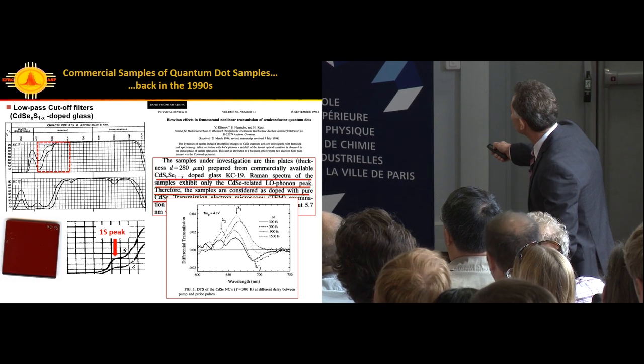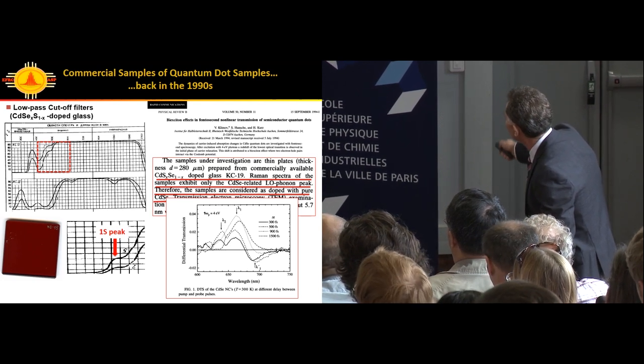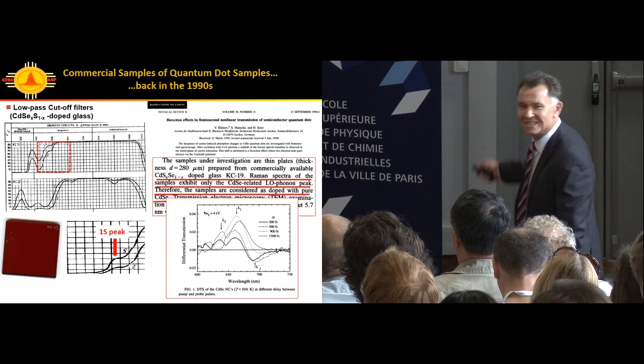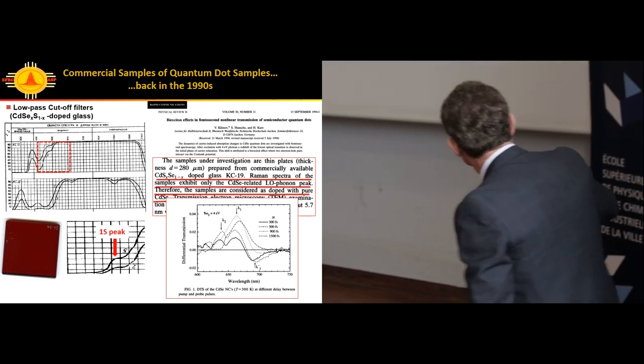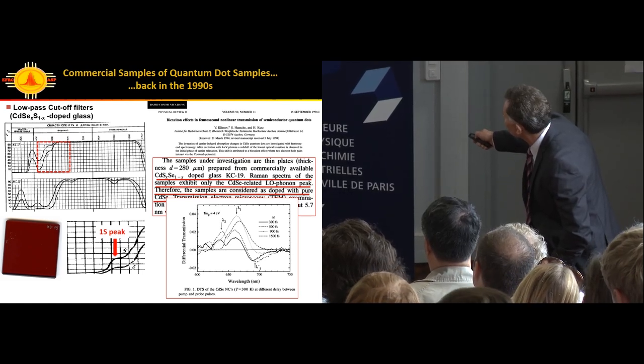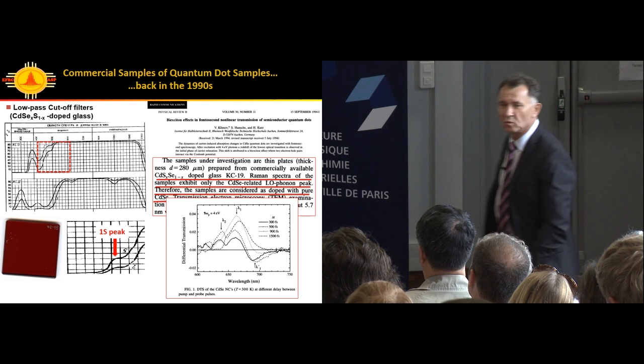With Neodymium-YAG I was limited by 20 picoseconds. With CPM I could look at picosecond time scales, and that's really something interesting. Typically with long pulses we see bleaching features. But if I looked at very short time scales, 300 femtoseconds, this is what you see. Very unusual - you see this derivative-like feature, induced absorption below the main transition, bleaching.